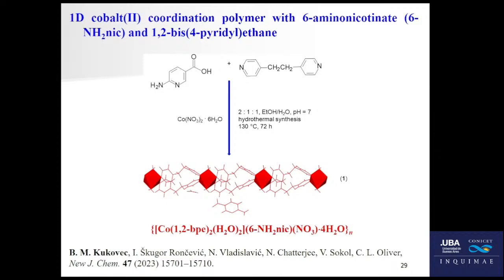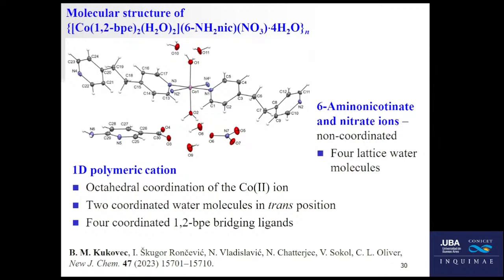So inspired by these results, we used again, in the previous example we had 6-hydroxynicotinic acid. Here we have 6-aminonicotinic acid, and not 4,4-bipyridine, but this bipyridine ligand, which is a bit more complex one. As I mentioned, this is 1,2-bis(4-pyridyl)ethane. So we reacted these two with the cobalt, again using hydrothermal synthesis for 72 hours at 130 degrees, and we get again a coordination polymer of some type. You can see it here.